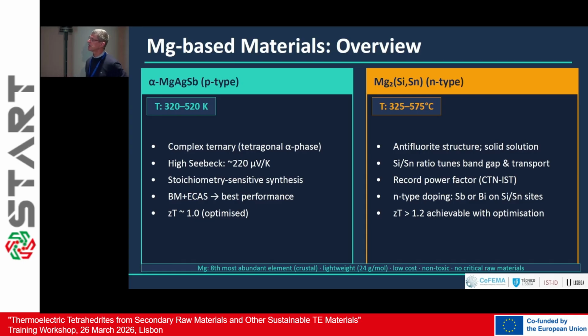So let's look at the alpha magnesium silver antimony. It's a p-type. So one is p-type, the other is n-type. It has a complex ternary tetragonal structure and a high Seebeck coefficient. However, it's quite sensitive to the synthesis. It can be prepared in different ways. We basically used ball milling and electric current assisted sintering, some kind of SPS. So they had quite reasonable ZTs. But we also developed a method to avoid the ball milling, just by induction melting and then normal hot press. So it's one possibility.